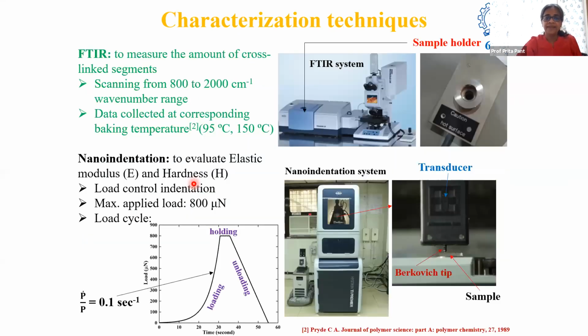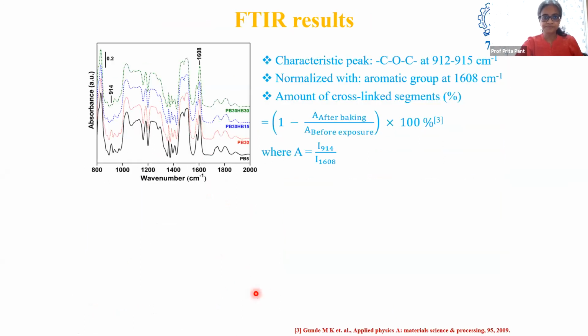Okay. And then we did measure the level of cross-linking using an FTIR system. And we also realized in doing this that the temperature at which you do your FTIR measurement makes a difference. So we did it at the baking temperatures, 95 degrees and 150 degrees. And then we indented those samples. They're all done in this constant P dot by P mode. We went to this particular maximum load, and this is the load cycle that we followed. So this is standard information.